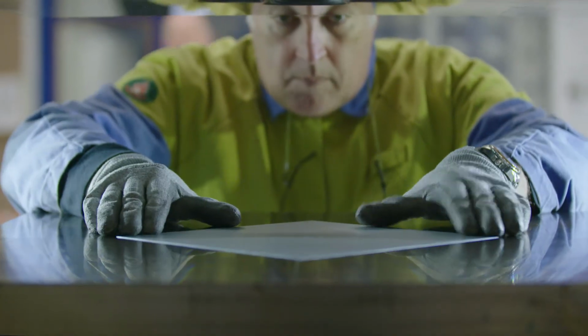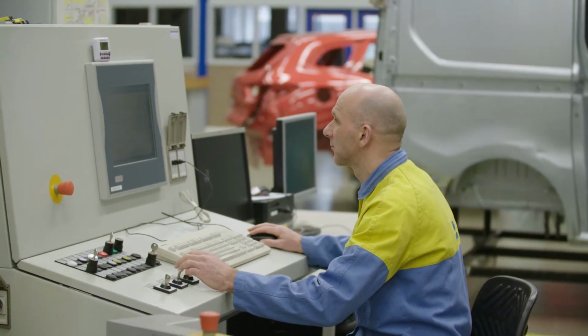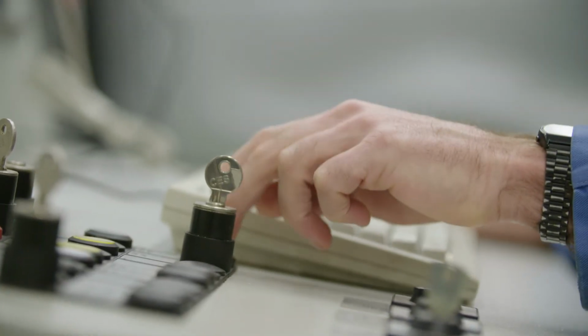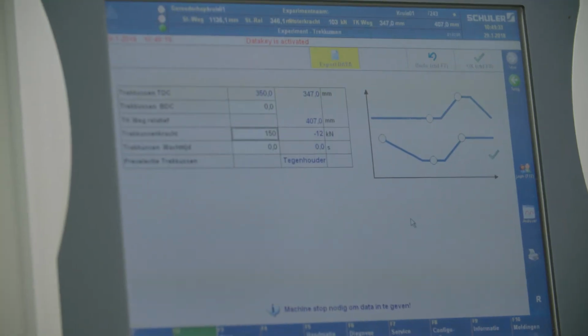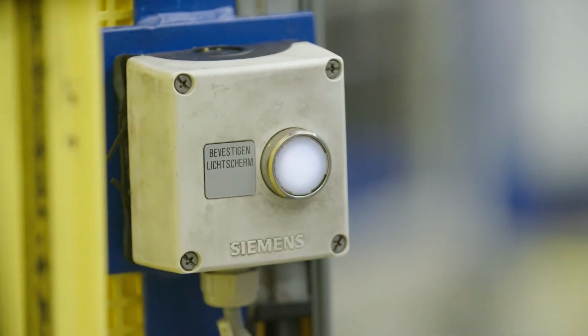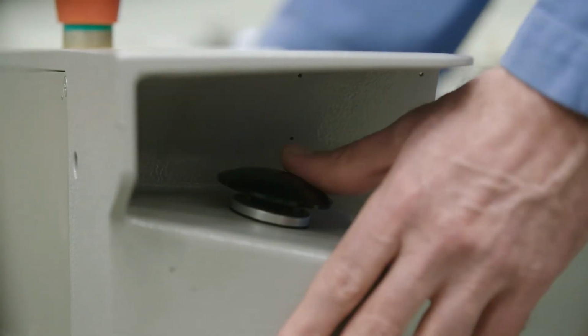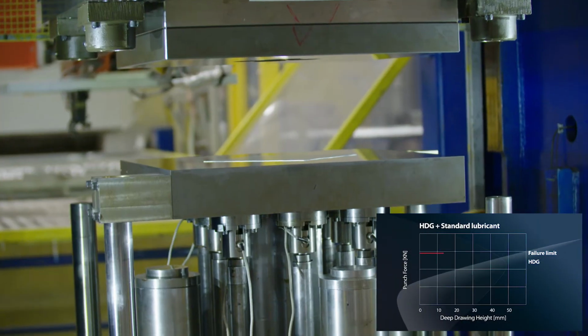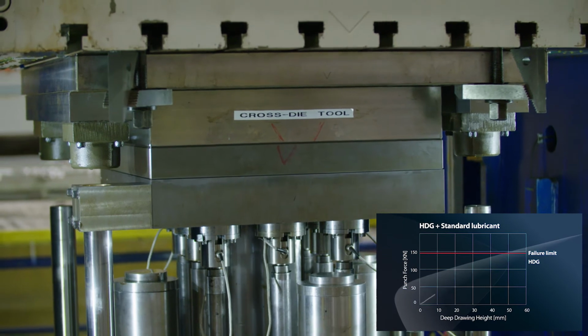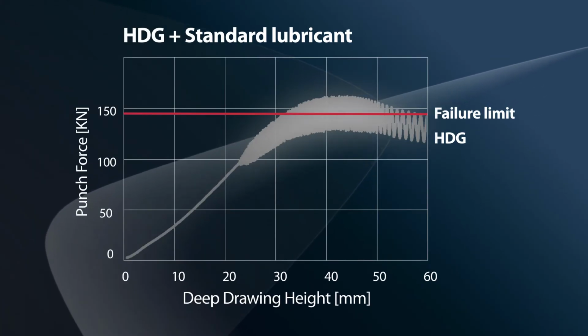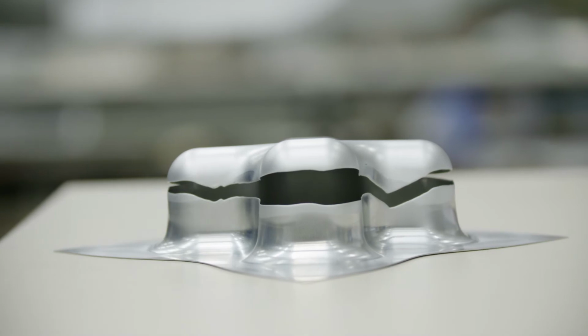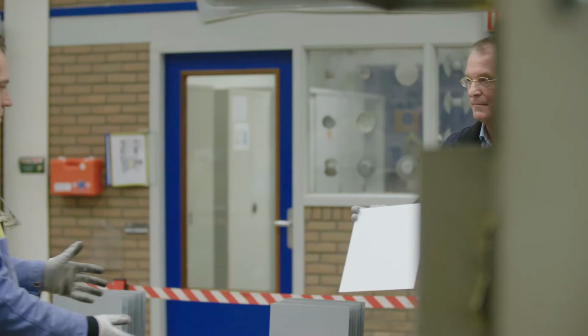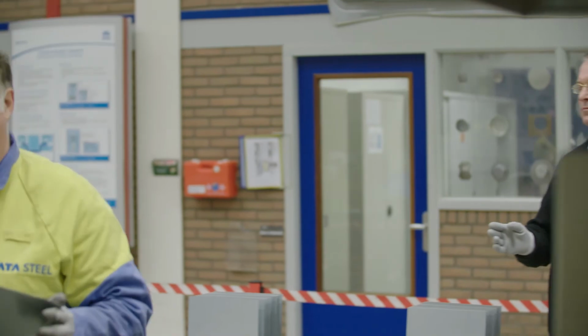A well-known phenomenon using hot dip galvanized with only pre-lube is stick slip, which results in strong deviation of friction forces and thereby a reduction in formability. The increase of the punch force due to stick slip is beyond the mechanical properties of the sheet material. One can hear the so-called screaming of hot dip galvanized, a sound which is disliked by people in press shops and induces splits. Now we perform the test with the same critical settings with PLT.